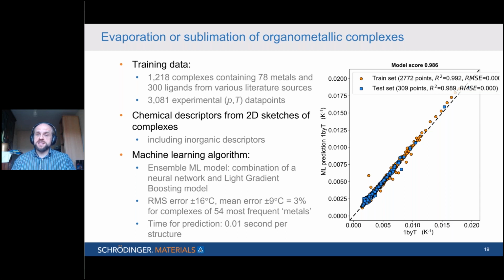The points both for the training set and the test set lie on the 45-degree straight line pretty well. The R squared is a measure of the quality of fit, and that's 0.99, so practically the optimum value of 1.0. The RMS error across the entire data set is 16 degrees Celsius. The mean error is 9 degrees Celsius, or 9 Kelvin, which is 3% of the evaporation temperature on average, if we restrict ourselves to the 54 most frequent metals that we had in our training set. And what's worth bearing in mind is that once this model has been created, it's very quick to evaluate. It takes a fraction of a second.